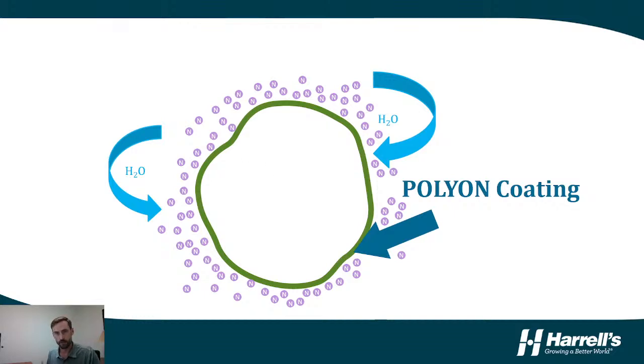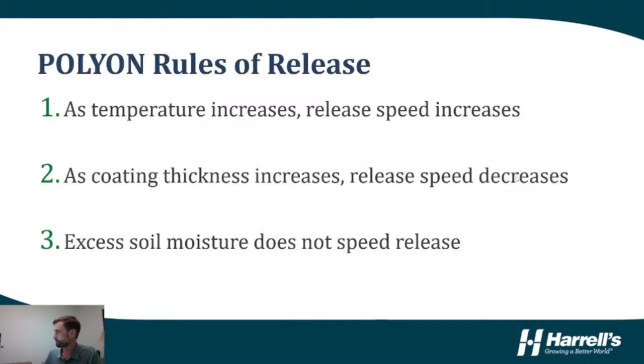So there are some fertilizer technologies out there that, if you apply them as a slow release material, you might only get 80% of the nitrogen actually released in a given growing season. Whereas with the Polyon technology, if you apply a pound, you're going to get a pound of nutrient release during that growing season. So the rules of release, without going into too much detail with Polyon, are that as temperature increases, release speed increases. As coating thickness increases, release speed decreases. And excess soil moisture does not increase release speed.